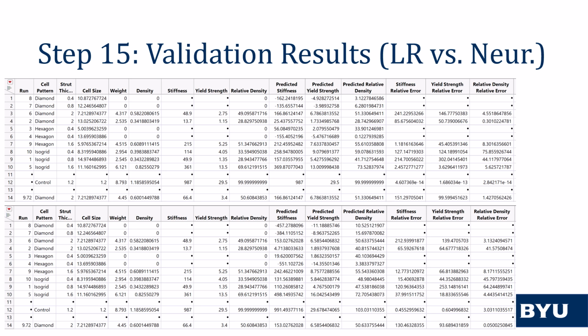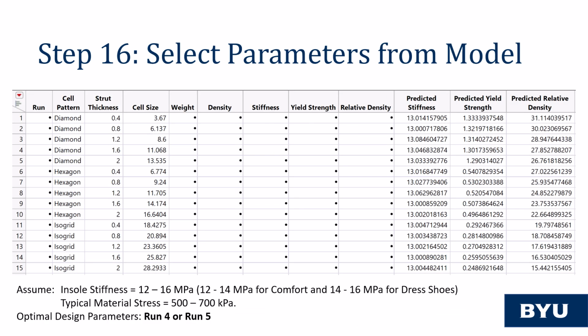The neural model, by contrast, is less accurate with the best prediction having only 3% error, but it demonstrates less of a spread with a maximum of only 253% error. It should be noted that both models are significantly more accurate for mid-values such as designs with a 1.6 mm strut thickness, while they get increasingly less accurate towards the extremes. This is likely due to the DOE samples that were unsuccessfully printed and thereby underrepresenting the design space in these extremes. Nevertheless, the models could be used to predict optimal design parameters for a given function.